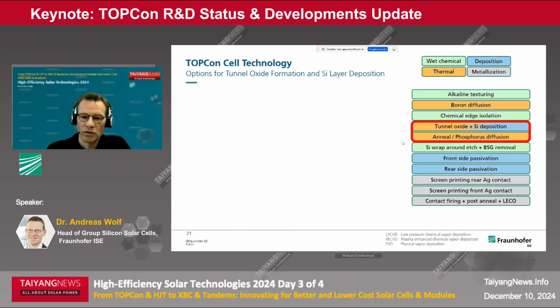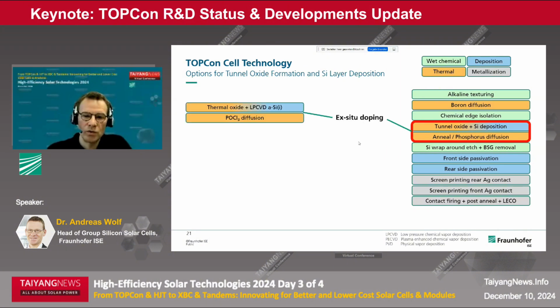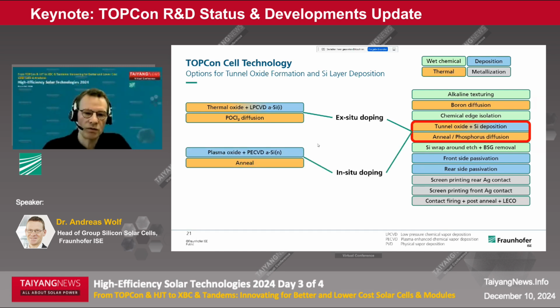The TOPCon system formation is also worth taking a closer look. There are different options in the market to do this. One widespread option is what we call the ex situ doping route, where you grow a thermal oxide in a tube furnace, and then an LPCVD process deposits an undoped silicon layer, which is subsequently, in a second process, doped by a POCl3 diffusion. But there are also in situ doping approaches out there.